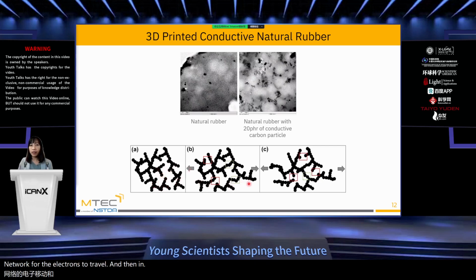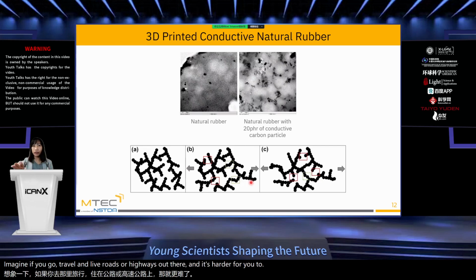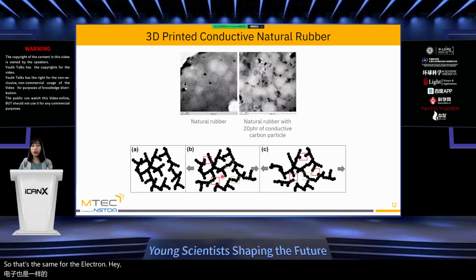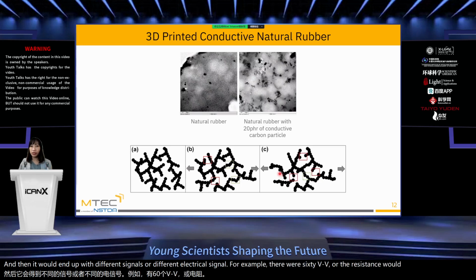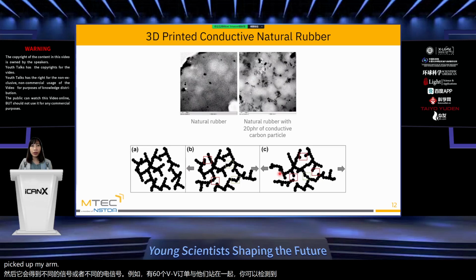And then in picture B, that's when you start to stretch, or when you make the network further away from each other. Imagine if you travel and there are fewer roads or highways out there, then it's harder for you to travel. That's the same for the electrons. When it's harder to travel, you end up with different electrical signals. For example, the resistivity or the resistance would change, and you can detect it by measuring the voltage, the current, or the resistance itself.